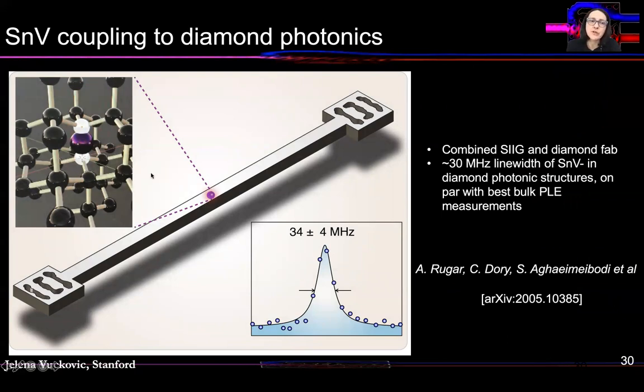Recently, we have shown that we can embed tin vacancy color center inside of such a diamond circuit with optimized couplers. We preserve very narrow line width, comparable to the line width of color centers in bulk. And we're now moving further to combining and interacting multiple color centers via diamond circuits.